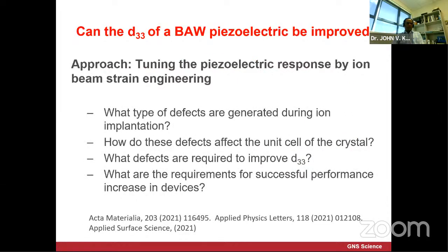So we have been looking at how we can improve the D33 of the piezoelectric bulk acoustic wave filter. One approach we came up with is, can we tune the stress by inducing defects in the crystalline lattice through ion beam implantation? Then look at how these defects affect the unit cell of the crystals, and also investigate what sort of defects are required to improve D33.